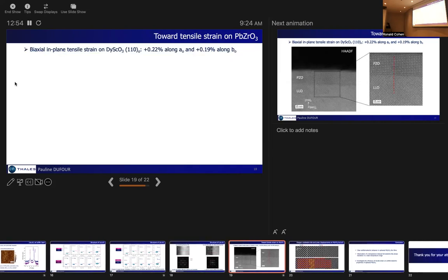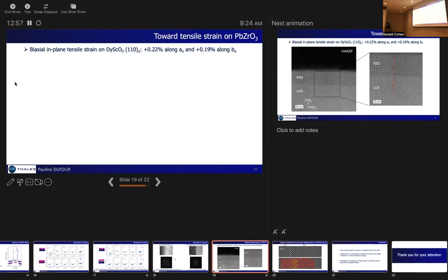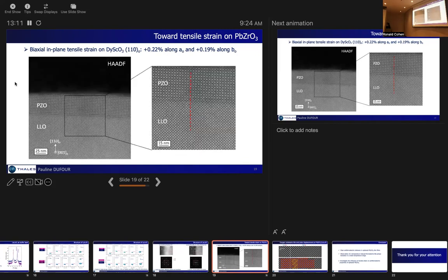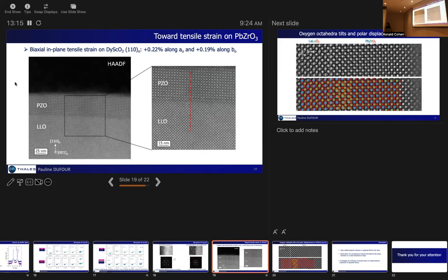So the final step is to add our lead zirconate on top of this buffer layer. So we grew 80 nanometers thick lead zirconate thin films, and we could see that we successfully managed to induce in-plane tensile strain in our films in the range of 0.2%. And even more, which is even nicer, is that on 8 nanometer thin films, you can see that we have a very, very clear interface with the lanthanum lutetate, which suggests that we can study in detail the atomic displacements of the atoms from the very first unit cells.